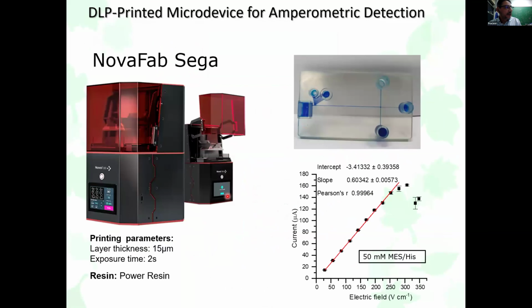Brenda also worked with other, cheaper machines. The layer thickness here is 15 microns for this Nova Fab, and we can show in this curve, for applications in electrophoresis, that the current has linear behavior against the applied electric field up to 250 volts per centimeter. That's pretty interesting for a microfluidic device. This means that the channel is small enough to dissipate the heat generated in the channel. So we can use this device up to this electric field, 250. Beyond here it starts to create bubbles, which is not good.